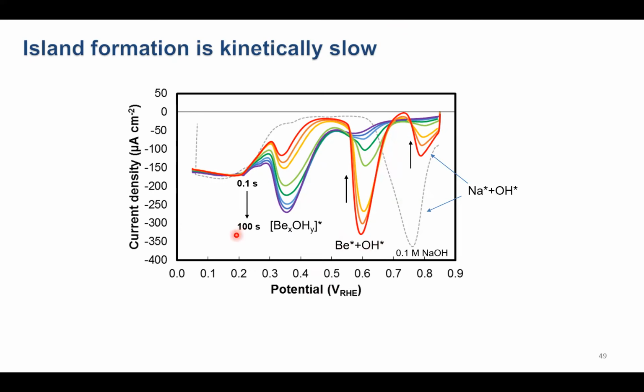However, as we increase the amount of time that we hold the electrode at this high potential, we give more time for these strongly bound beryllium hydroxide islands to form on the surface. We get this first order phase transition and these high potential peaks disappear. Most of our hydroxide is then stuck on the surface down to very, very low potentials, actually overlapping with even hydrogen adsorption. And so we have to start adsorbing hydrogen on the surface to start kicking off the hydroxide.